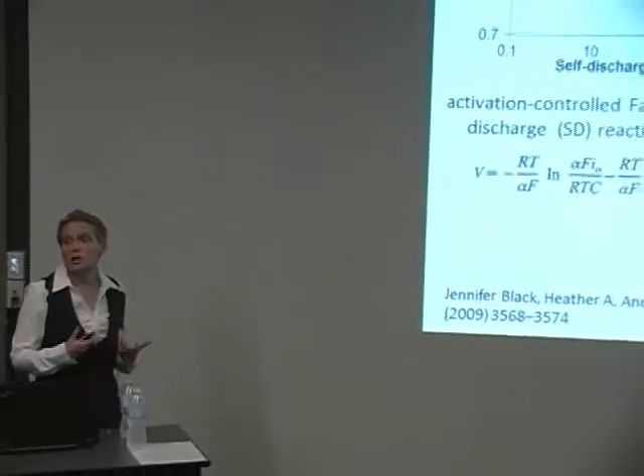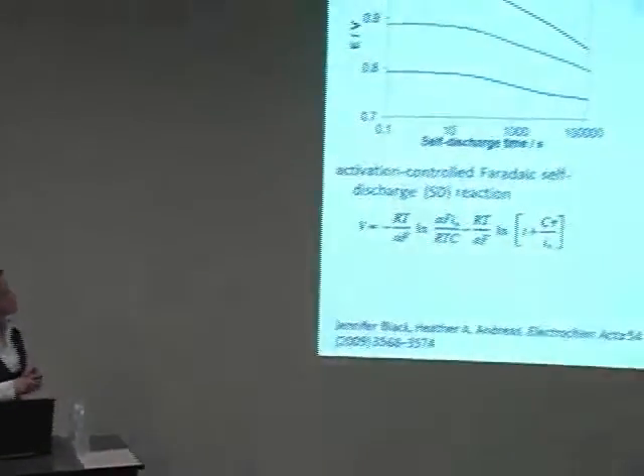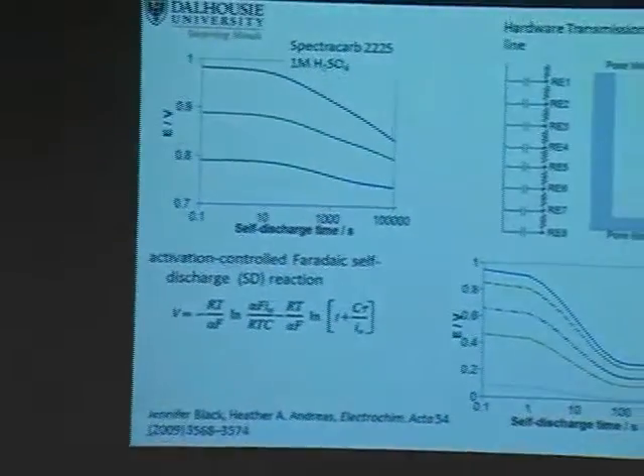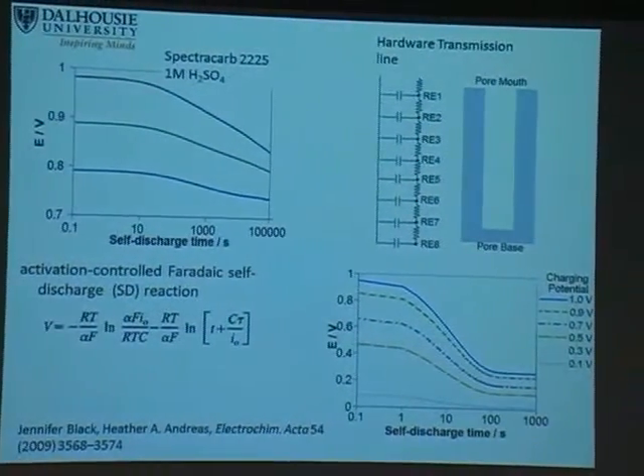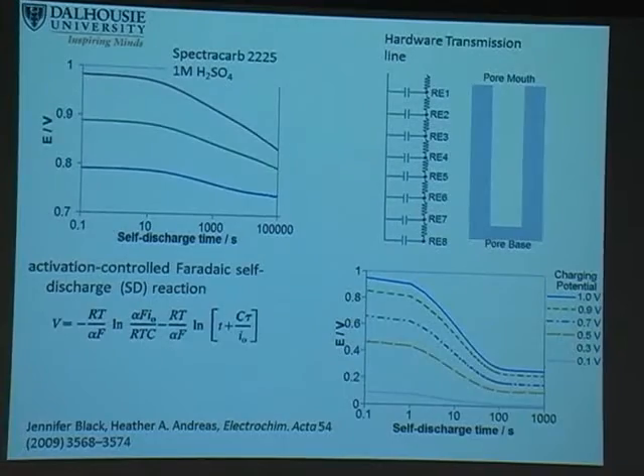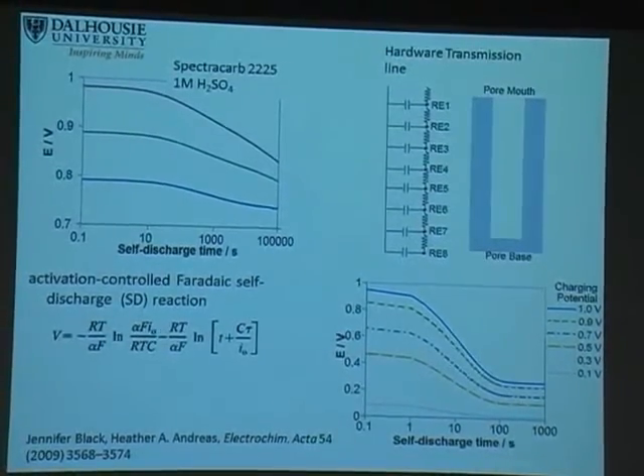And what we saw with carbon is that, in fact, that slope is very different. That slope depends on our initial potential. We see that with charge redistribution. We see that with an initial potential change, our slope changes. And so what this is suggesting to us is that in this carbon that we're using, one of the main reasons it appears to lose charge is charge redistribution.